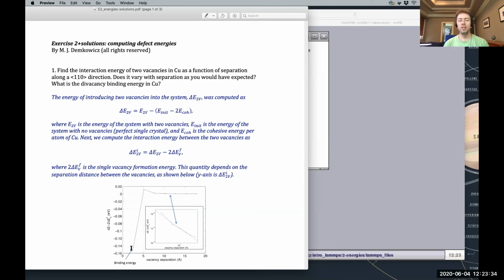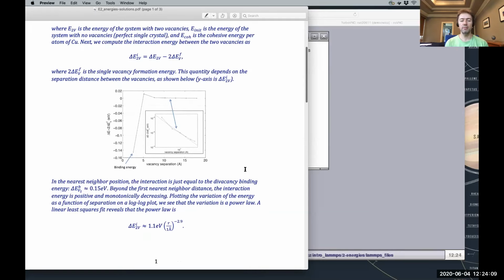Right? So those of you who attended the seminar yesterday on radiation damage might remember that when vacancies come together, they can cluster. Well, why do they cluster? They cluster because when they get together, they bind, right? And that binding comes from the binding energy. With everything that I've told you about making models in LAMMPS and running relaxations with LAMMPS, you can compute this binding energy. You can compute the binding energy curve as a function of inter-vacancy distance. Okay? So try that out as a little exercise to see if you can do that.